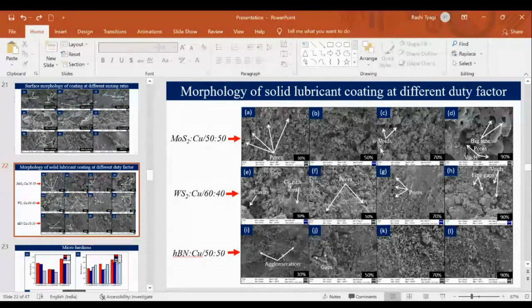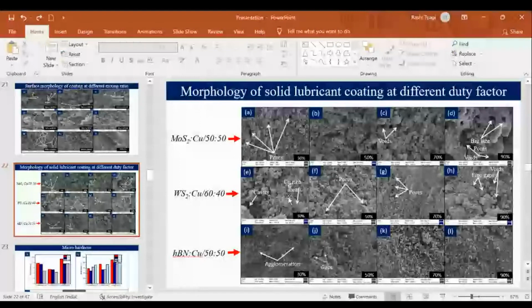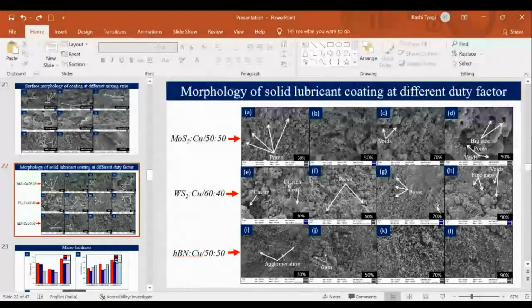So we observe that in this coating, at 50% duty factor, we get the minimum pores. See, there is a minimum of pores in this coating as compared to the other processes. Also, voids can be seen in some coatings. Similarly, in the WS2 powder coating, pore formation was lower at 50%. In the HBN plus copper coating, pore formation was lower at 70% duty factor. So we have to check by trial experiment or by surface morphology analysis at which duty factor we have obtained a good coating.